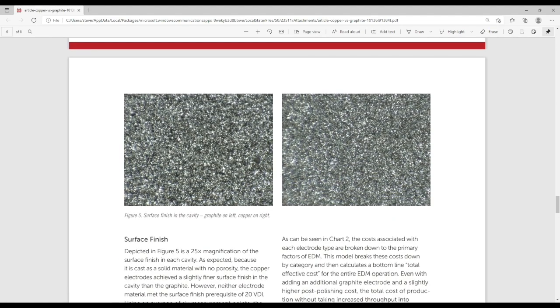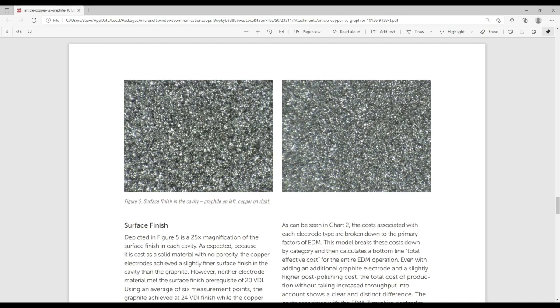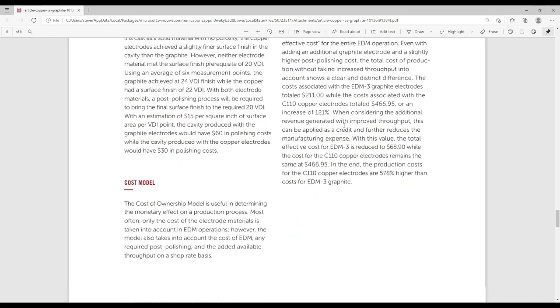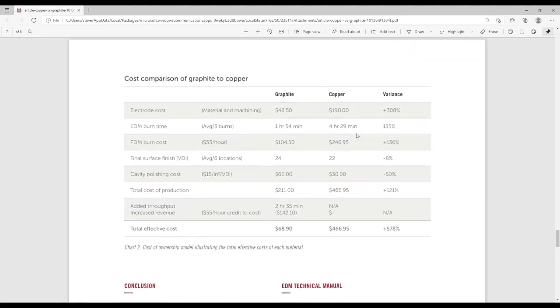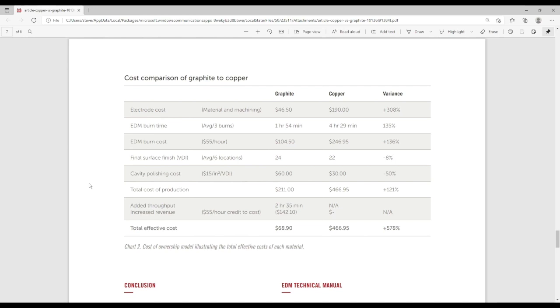And this is just a 25 times comparison. On the left is the graphite, and on the right is the finer finish of the copper. And here's kind of a breakdown. This shows the cost of the material, graphite versus copper. It's like a 300% difference. Your burn times are faster by a lot, 135%. And this chart kind of explains the need for people to move to graphite for a majority of the work that's done in steel.